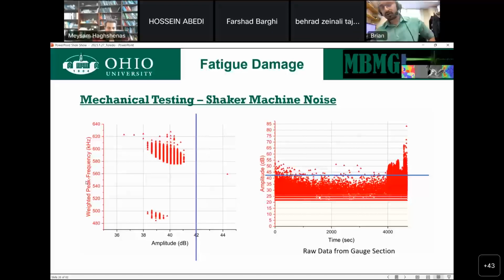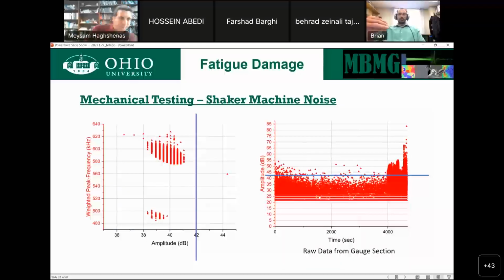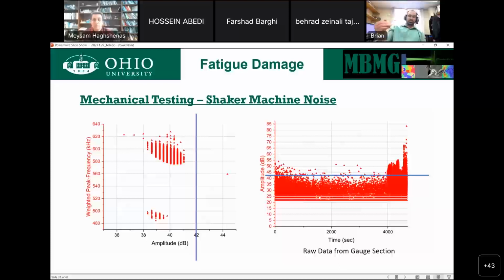But we did this by having a sensor mounted directly to the shaker and a sensor mounted to a sample on the shaker. By doing this, we're able to see what the shaker produces as far as noise in this sensor, and then remove anything below that line. And what that tells us is when we're talking about amplitude, how loud the signal is, for the machine we're using, anything on the order of about 42 decibels or lower has the potential to be just the machine in its standard operation. Anything above that doesn't exist on the machine, which means it has to come from the sample. And that's where the information for damage comes.